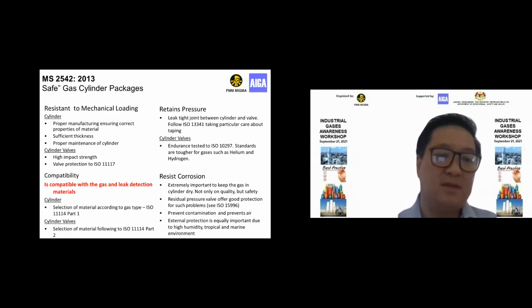Gas compatibility is, as I said just now, ISO 11114 identifies the material used for cylinders according to the gas stream. 11114 part 2 is for the valve itself, because normally valves are made in brass and not steel. There are steel valves for certain gas materials, but the vast majority of valves are brass. Retains pressure, so there is leak testing, which I will go through a bit later on, ISO 13341, and also endurance testing of the valve, which is ISO 10297.